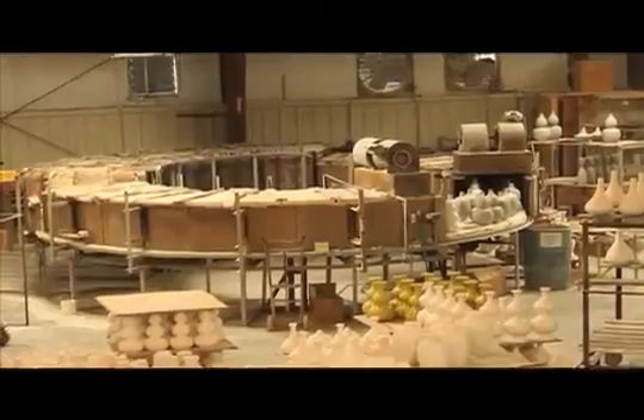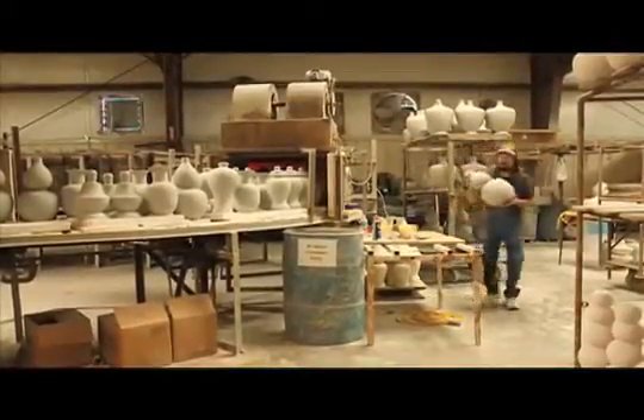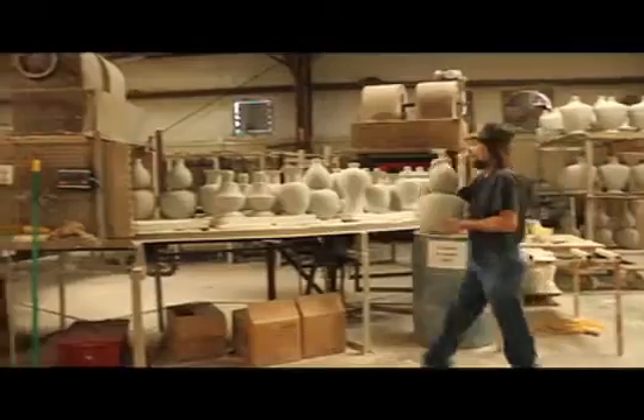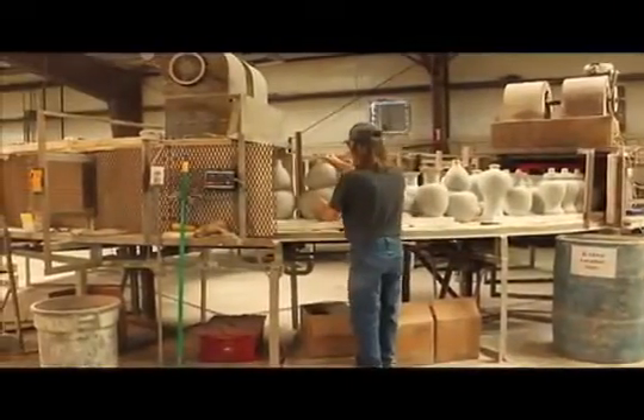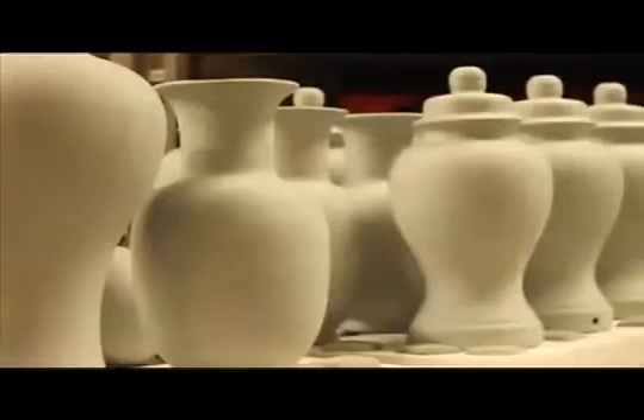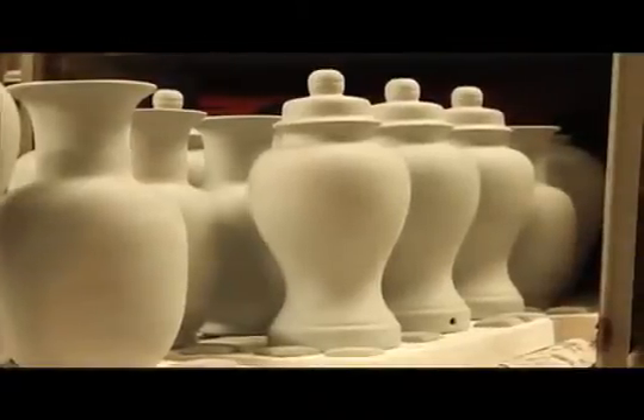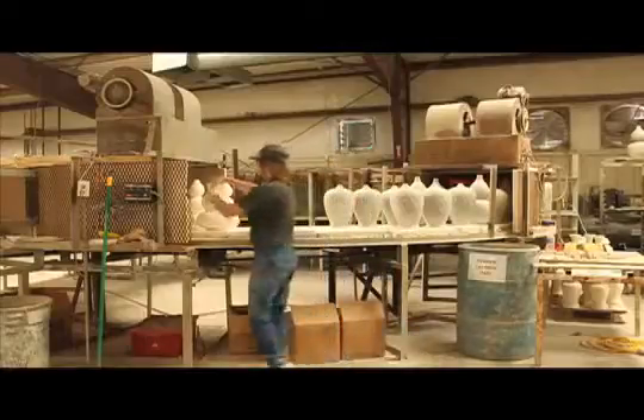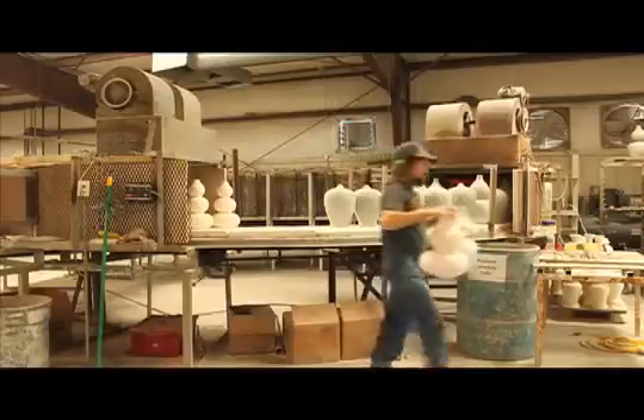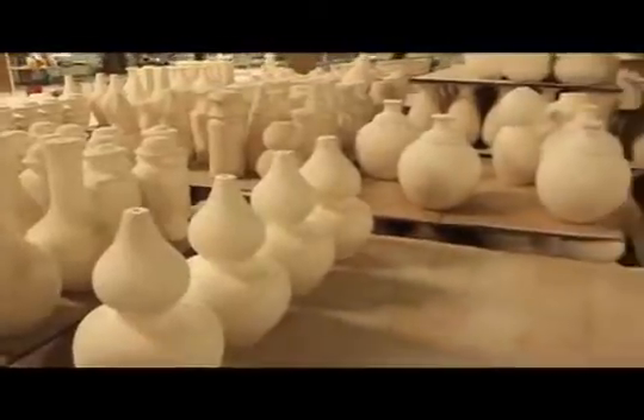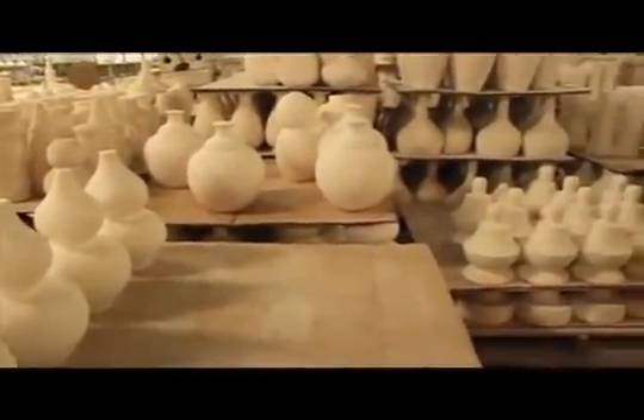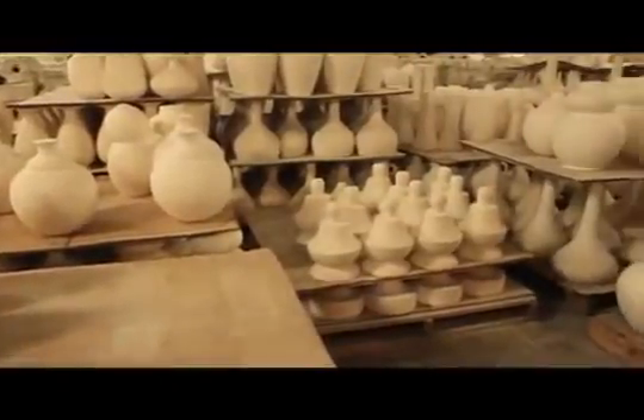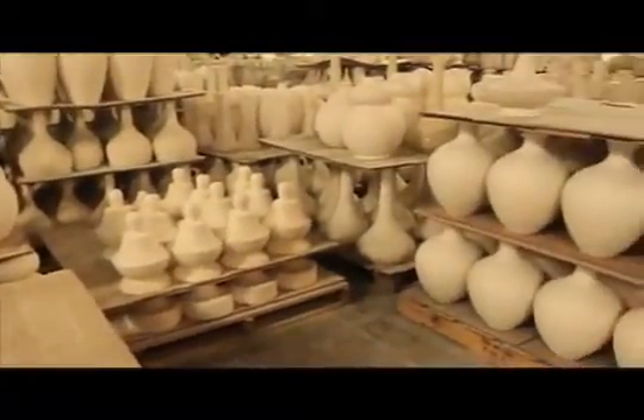Our kiln is an electric cycle kiln. A rotating table carries the ware through 3 firing stages. It takes about 4 hours for ware to make 1 full rotation through the heat up, firing, and cool down process. The firebox, which contains the heating elements, fires greenware to 1750 degrees. When the pieces come out of the kiln, they are a strong, hardened, white ware called bisque. Bisque pieces are stacked on skids waiting to be glazed or decorated.